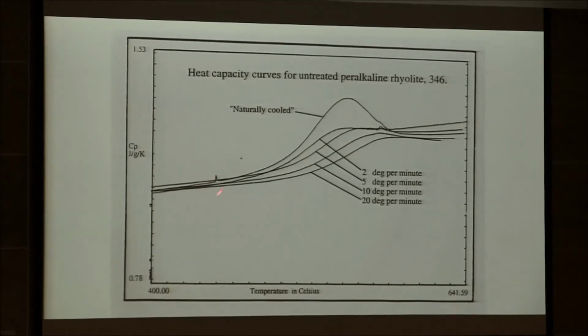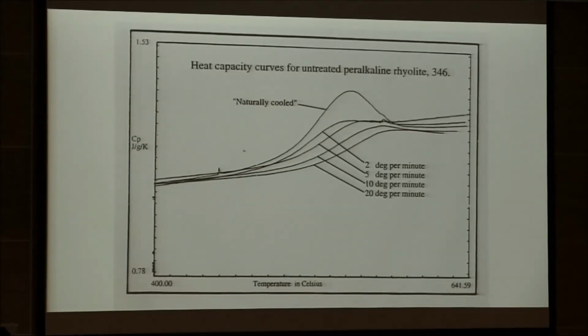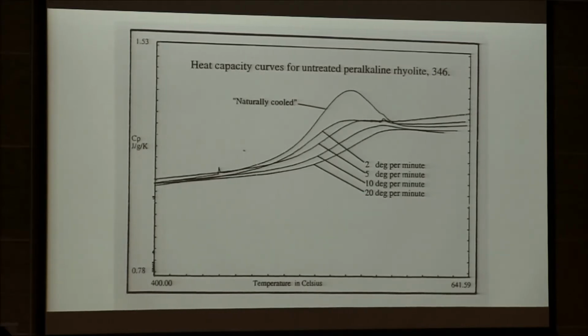So here we go. This is the raw data. This is from another sample now, but it's raw data. Here you see naturally cooled. I heated it up, and this is the signal that I got from the calorimeter. Then I leave the sample in the calorimeter and I cool it down at a known rate. That means I decide the cooling rate of the glass. And then I heat it up again and record what the calibrated signal is for that cooling rate. And then I cool it down at another rate, half as fast. I heat it up again, and I get another calibration curve. And I walk myself here, back and forth, back and forth, to a range of cooling rates that I can access in the lab.